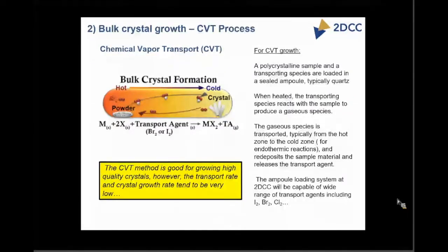So the second area then, in terms of the 2DCC for equipment that's being installed and developed, process being developed for, is chemical vapor transport. If you're not familiar with this process, the basic idea is you use a transport agent to transport material from a source to the crystal. So you start by putting a polycrystalline sample and a transport agent in a sealed ampule, typically a quartz ampule.